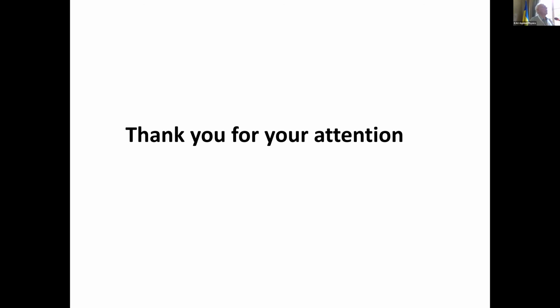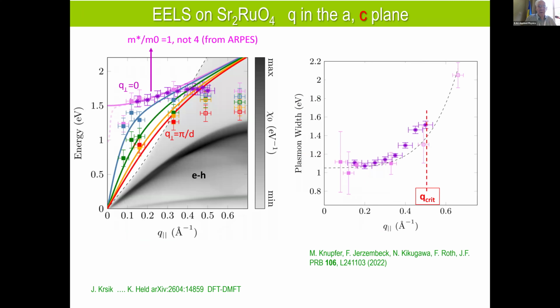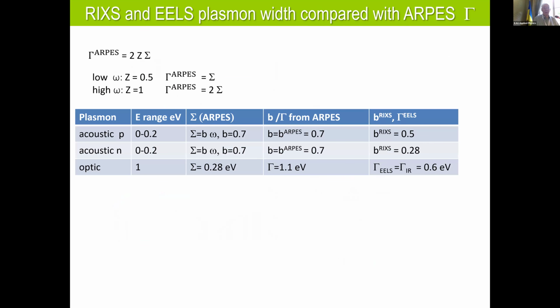Thanks. I have 2 questions. Could you go to this nice table which compares ARPES and RIXS lifetimes or widths? So there's this formula gamma ARPES equals twice sigma. This is standard in ARPES, that the scattering rate is twice the sigma from ARPES. Then this gamma ARPES you compare to gamma RIXS, and the conclusion is that it's roughly similar for all of these cuprates. The second line shows that at low energy we take a Z of 0.5.